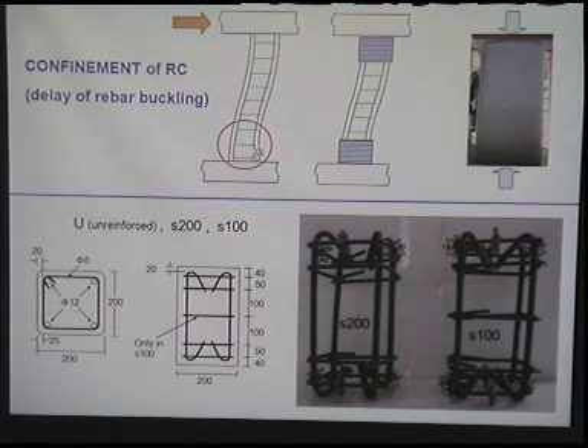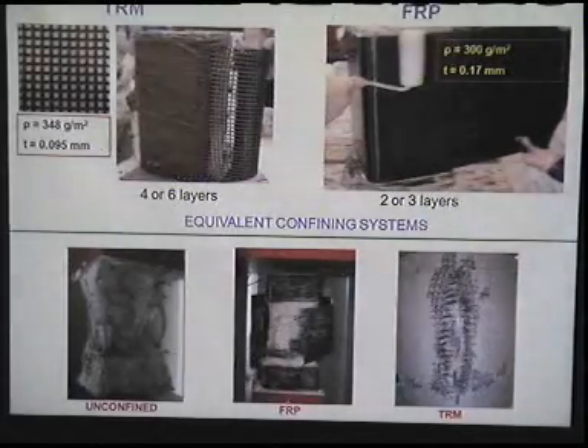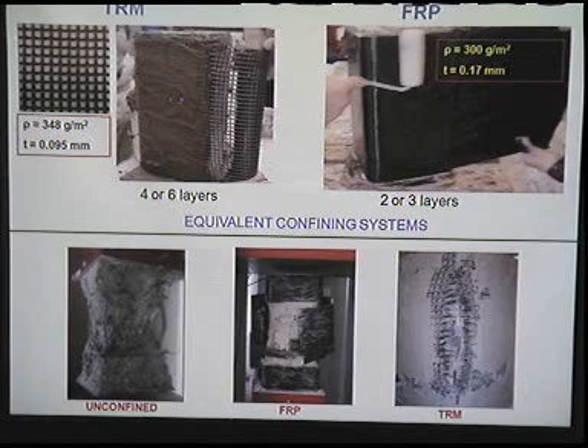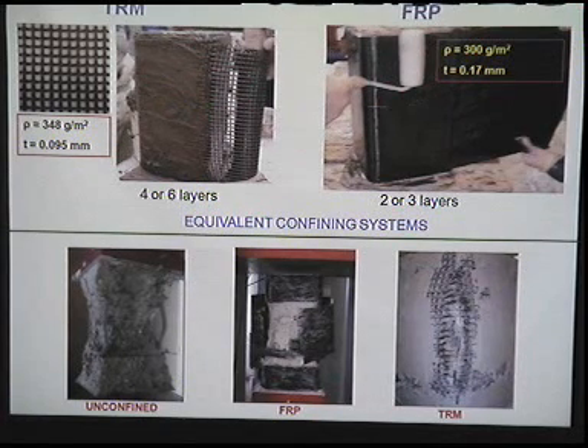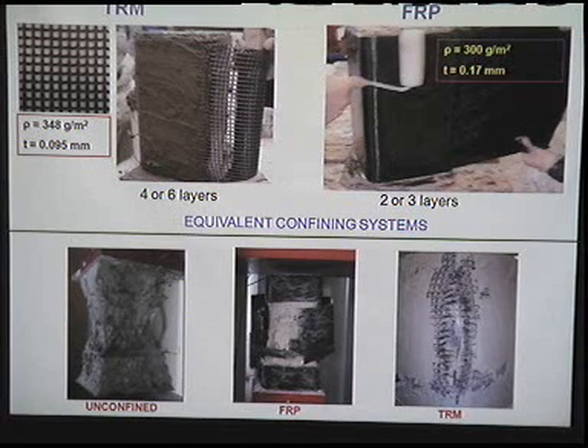And to have a good understanding of that, we started with small prisms, with small cross-sections, 20 by 20 centimeters, confined with FRPs and TRMs. I'll show you some photographs. You see one of those confined with the TRM system, and an identical specimen wrapped, confined with the FRP system. Those systems are equivalent. That is, we have exactly the same amount of fibers in the circumferential direction. The only difference is in the matrix. Here we have epoxy. In that case, we use a cement-based matrix to bond the fibers.